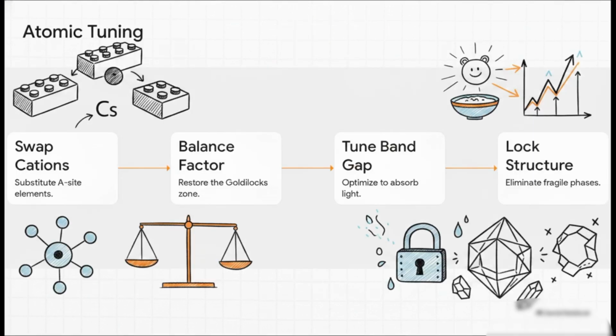Enter compositional engineering. Going back to our Lego analogy, scientists can literally swap out individual atoms in that central A site. For example, by carefully substituting just a tiny fraction of the original atoms with a totally different element, like cesium, they change the physical size of the internal components. This pushes the tolerance factor right back into that Goldilocks zone. By doing this, they effectively tune the band gap to absorb way more of the sun's light, while simultaneously eliminating those fragile non-photovoltaic phases. The whole crystal structure locks tightly into place, and the material suddenly becomes highly resilient to heat and moisture.